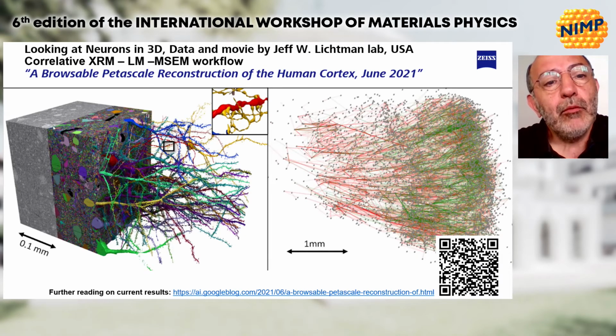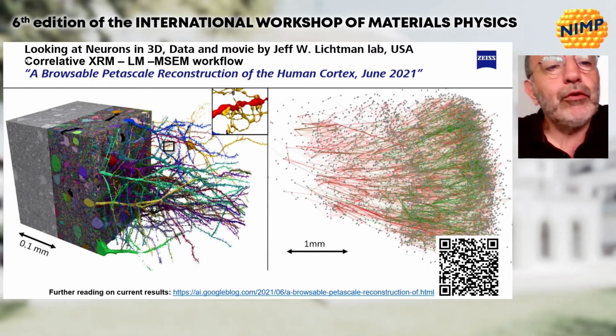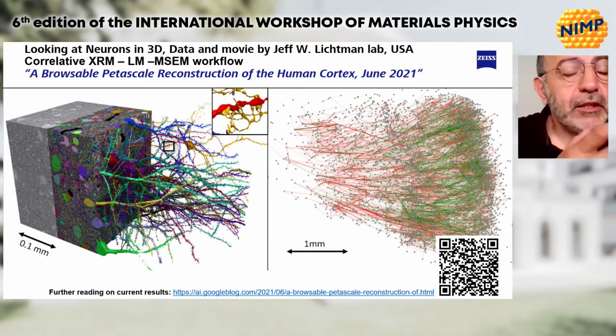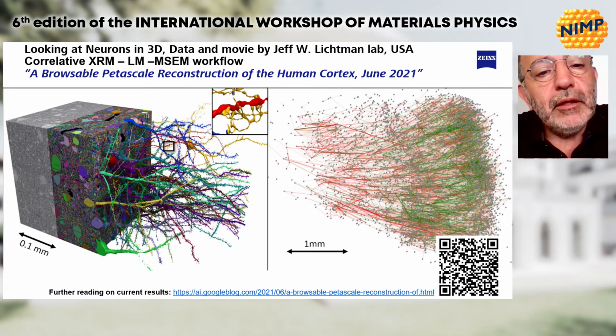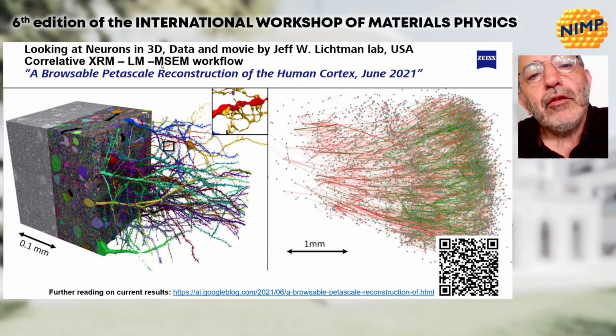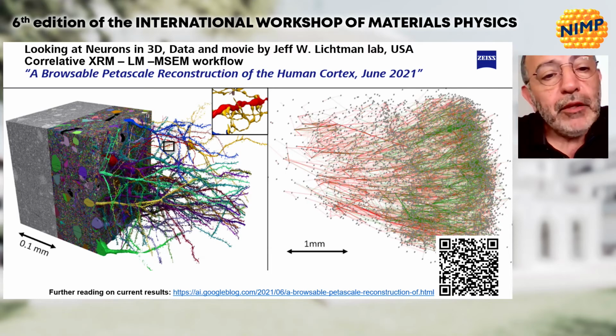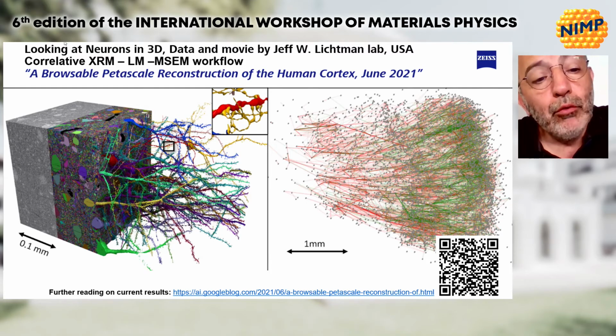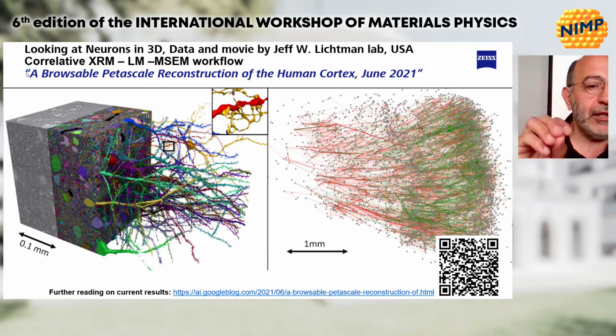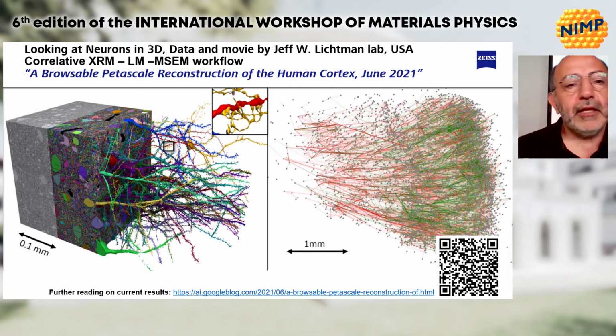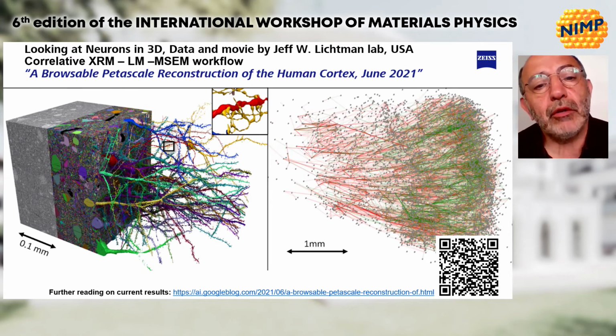Just to give you an idea of what this means, this is a very recent publication, which was performed also in a correlative workflow using XRM, also X-ray tomography by synchrotrons or by in situ lab systems, like in this case, using correlation with light microscopy, and finally using the multi-beam SEM to take from these very huge samples nanopixel resolution for the full cube, not only for a dedicated area of interest, but the full cube. It was performed with a resolution of nanopixel.